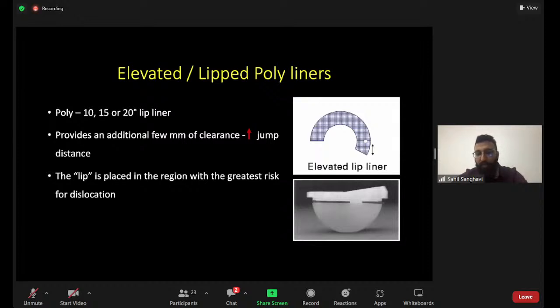So what is the meaning of this lipped liner or elevated liner? It means that there is an elevated rim. As you can see in the clinical photograph here, there is an elevated rim in the polyethylene, and this acts as an extra cover to the liner. The advantage of this is that it provides you an additional few millimeters of clearance and thereby increases the jump distance. So this lip is placed in the region with the greatest risk for dislocation.